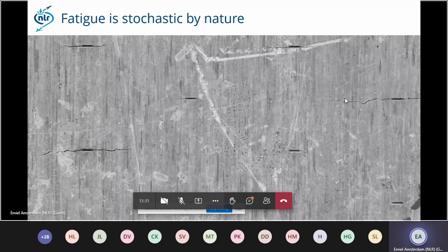Another thing to mention is that fatigue is quite stochastic by nature. Here you can see a SEM image of the surface of a specimen where we made laser defects on the surface. You can see that cracks from some laser surface defects are growing, as you can see here for this defect, but around this defect there isn't any crack growing. Here there's a very small crack on either side of the defect, and here's again a very large one. So it really depends on the size of the defect, the shape of the defect, and the microstructure surrounding such a defect, whether a crack is fast, and if it's growing or not growing.